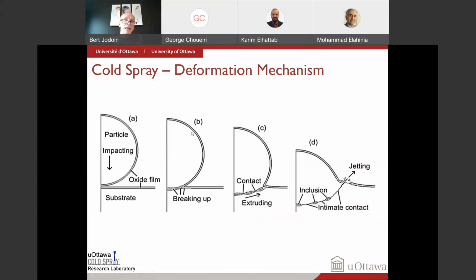So if we look again at this diagram, this tiny layer here at the interface, that's where all the impact energy is trapped. Some of it to induce dislocation and perform deformation, but most of it in terms of heat. And that's why this tiny layer here now is almost viscous like a fluid. So that's how it deforms.